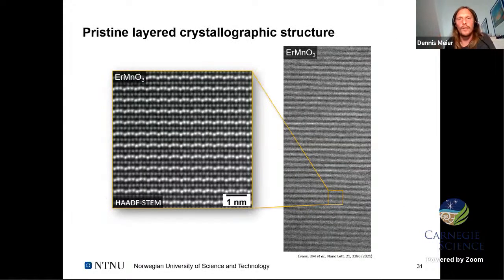We stick with our model system, erbium manganite, and you've already seen this image before, where we have a nice STEM image of the erbium atoms and the manganese layers. The only thing I would like to show you here is that these crystals usually have a very perfect structure. Even if you look over larger length scales, we always have this nice layered structure.